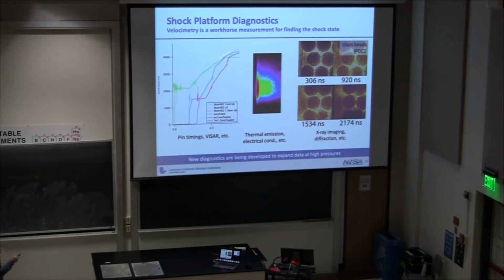And so these give you these wave traces that you find like this. And so this part here, let's ignore this part, but the flat part on the top is basically the shock physics part. So you've shocked the material up, all of a sudden it wasn't going fast, now it's going fast. And so that's your number that you're going to pull out through this. This particularly is a velocimetry trace. So this is basically a radar gun is all you're asking here. So that tells you your pressure condition that's fine, or your density condition, but you might also want to know what your temperature is.